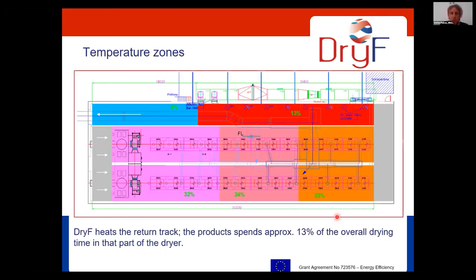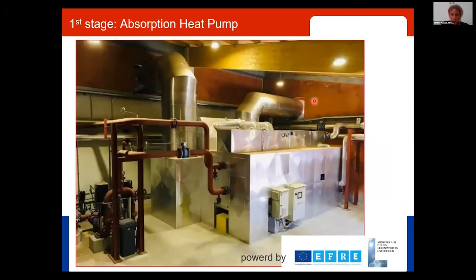When you have a bird's-eye view of the dryer in Uttendorf, this is a four track dryer where the product spends most of the time at temperatures of maximum 90 degrees. And on the return track, this is the last track here above, we can do the final drying. So the product spends about 13% of its drying time in this hot section. And this is the DryF section. A duct was bolted on the building with a fan and a heat exchanger supplied from the DryF heat pump. And here we can provide higher temperatures to do the residual drying.